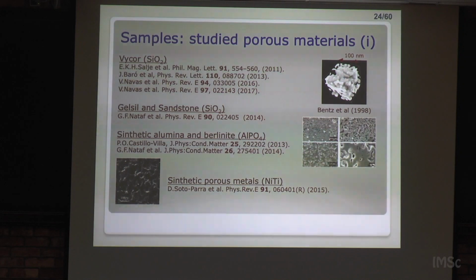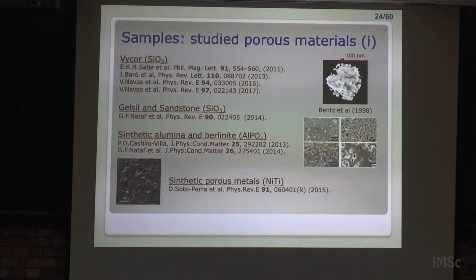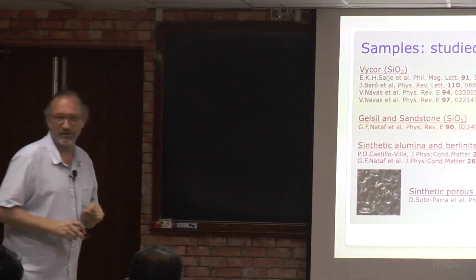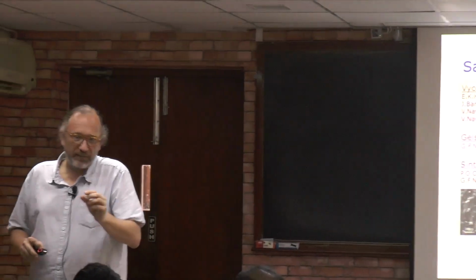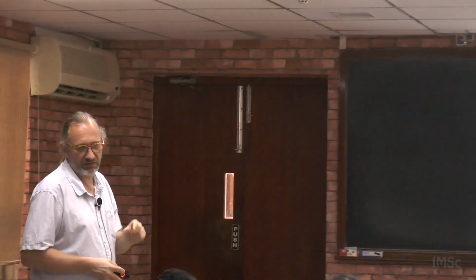So you have a crack. The crack is generating a sound. And this sound travels along the sample, then enters into the plate and reaches the sensor. That's it. Okay? It is impedance matched with the plate, which is usually steel. It's a steel plate, and the distance between the sensor and the sample is 1 millimeter.